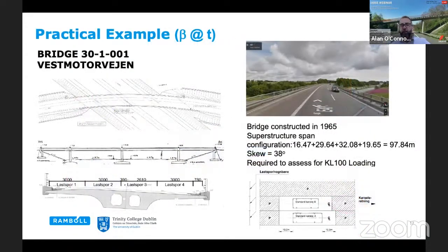So I want to show you another example from the perspective of the application of the methodology. This is the Vestmotorvejen Bridge, which was constructed in 1965 and has superstructure span configurations varying from 16 meters up to 32 meters, with a total structure length of 97 meters. Again, a relatively heavy skew at 38 degrees, and again it was required to document a class 100 rating for the structure. The problem, as you can see in the photograph here, is that there's an emergency lane on the structure. The problem is when the class 100 vehicle is located in that emergency lane in a torsion limit state case, and the structure was unable to document adequate capacity in that regard.